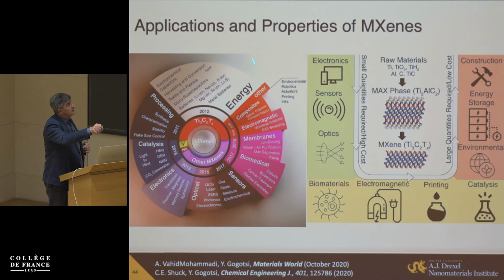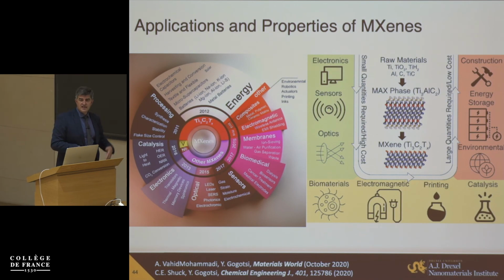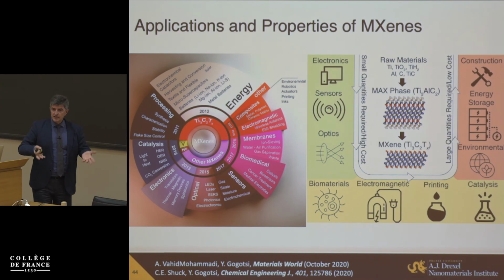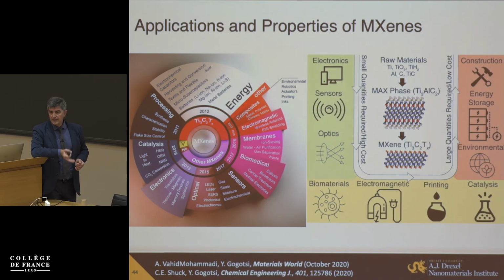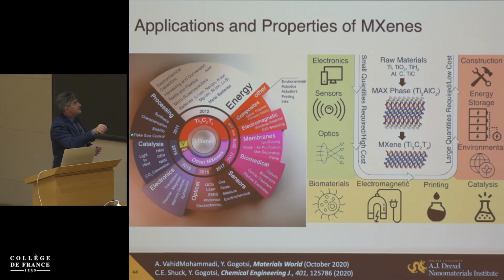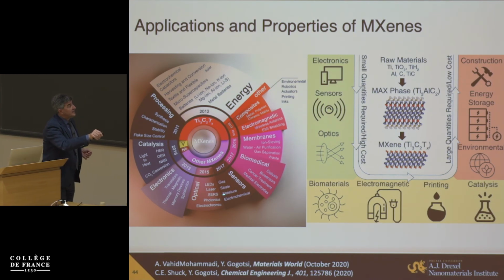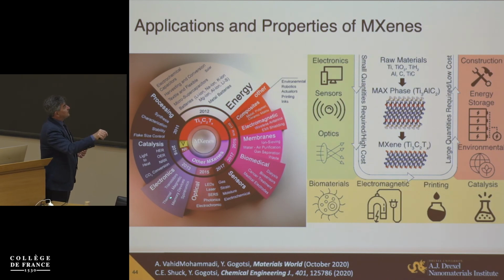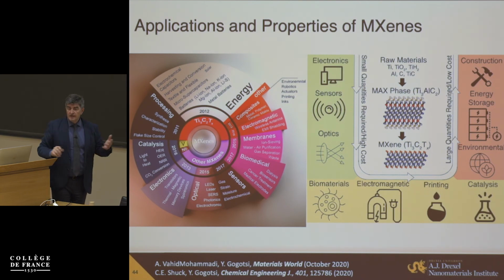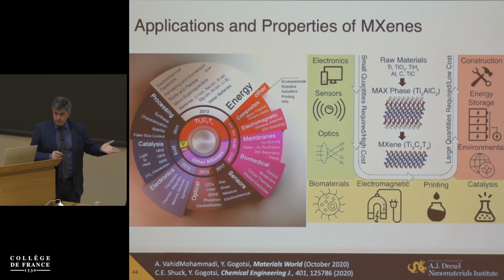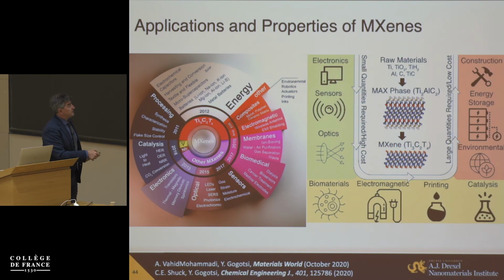And as you see today, still a large part of research is going on in batteries. I didn't talk about metal sulfur batteries. Linda Nazar was the first to show that MXene again can trap polysulfides, absorb strongly, and demonstrated very stable performance with several MXenes in lithium sulfur batteries here. But there are many other applications where again conductivity is used, in electronic applications, printable electronics here. We can talk about HER, for example, where several MXenes were predicted actually to be very close to platinum, and definitely molybdenum carbide-2 MXene outperforms significantly molybdenum disulfide, and applications are possible here.